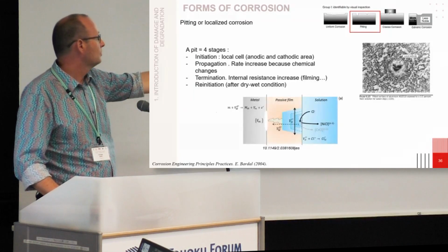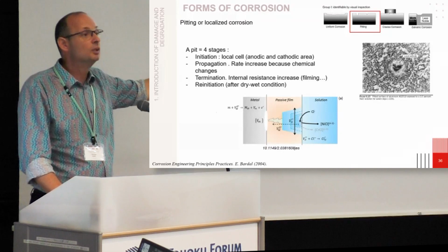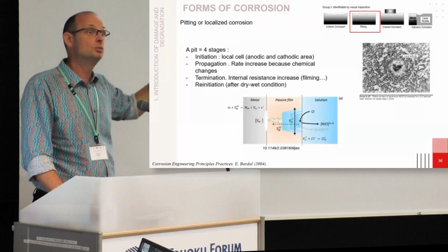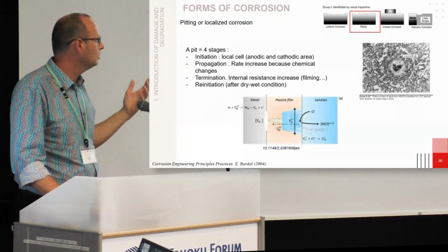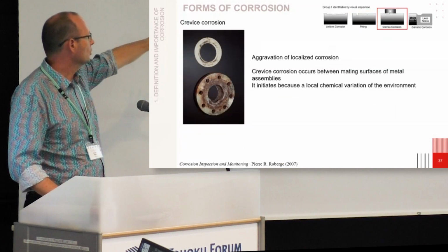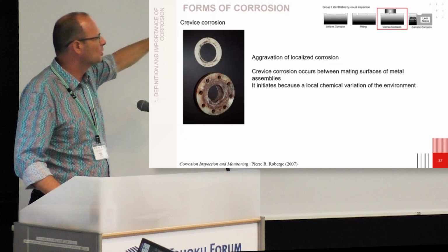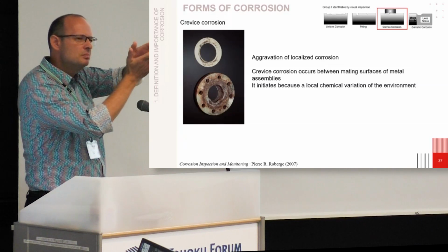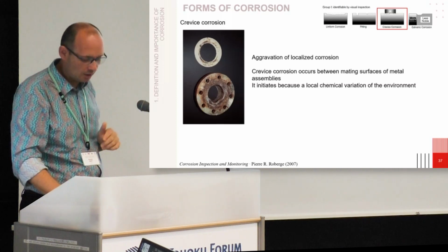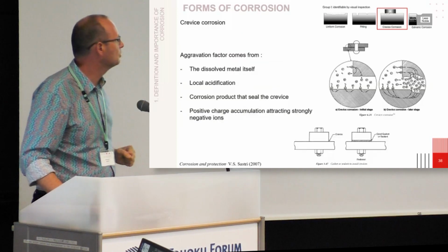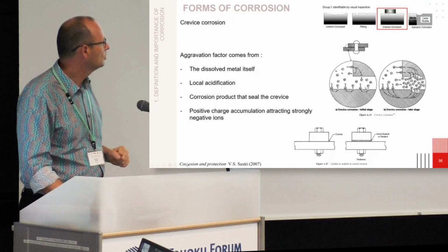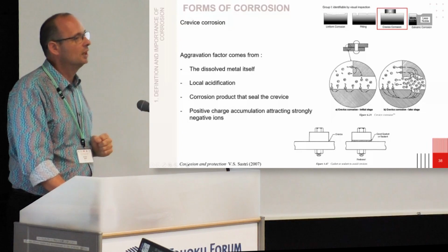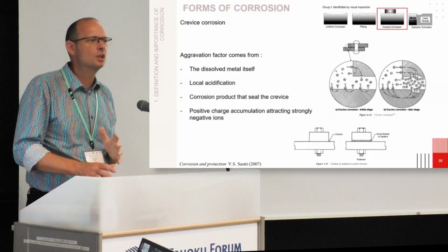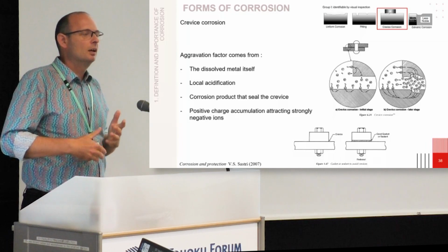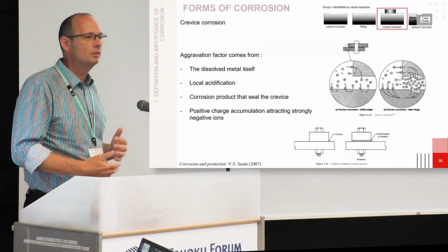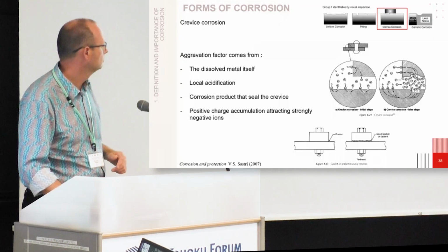We still, with pits, for example, try to develop some models to understand. I told you, we are scientists. We want to know. So we keep on going to understand what happened. Another kind, crevice. It's because there is some water going between two pieces. You change the environment. There are some very specific models here. So you see at the beginning almost nothing, but with the electroneutrality of the solution, you start to have ion diffusion, the ion concentration changes, and you change the environment. Material is not safe anymore, and you have dissolution.